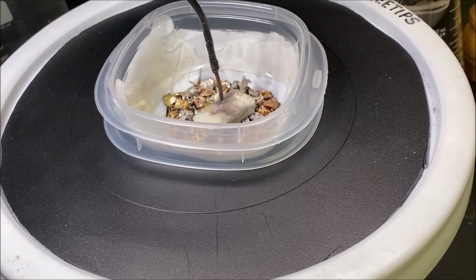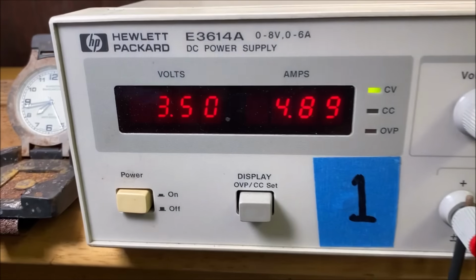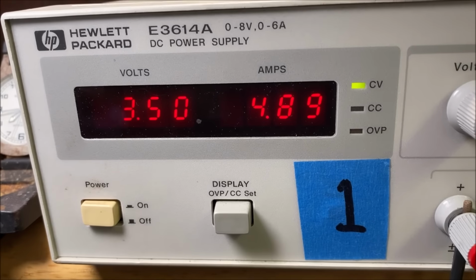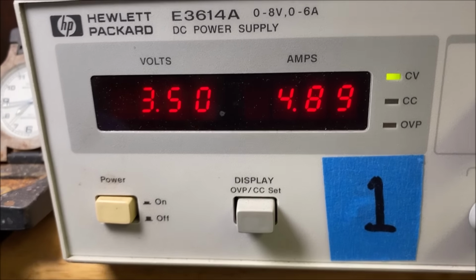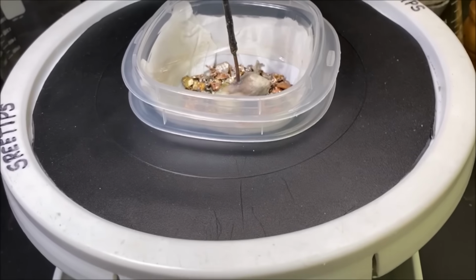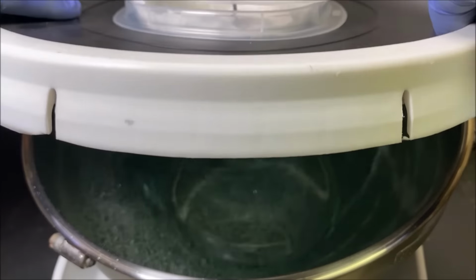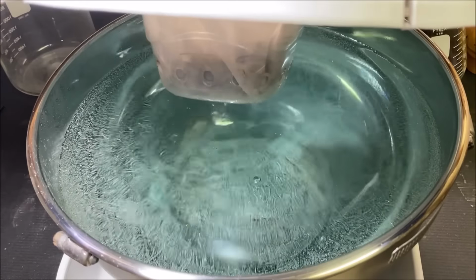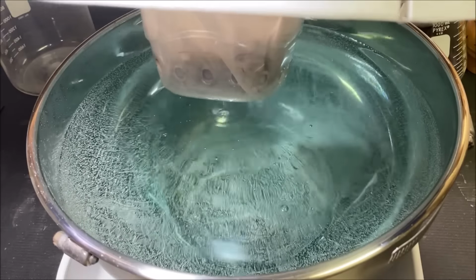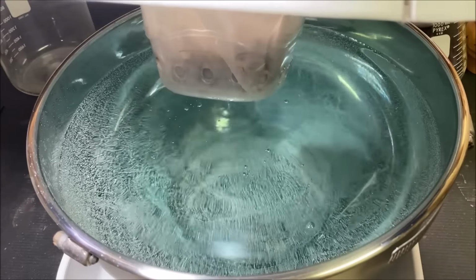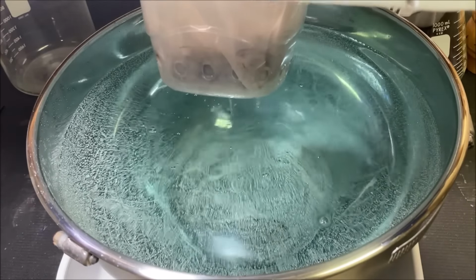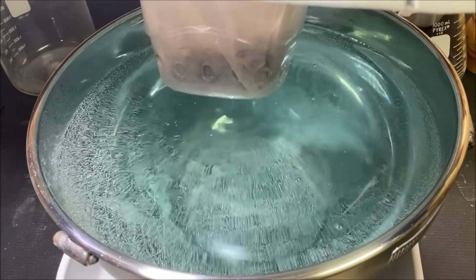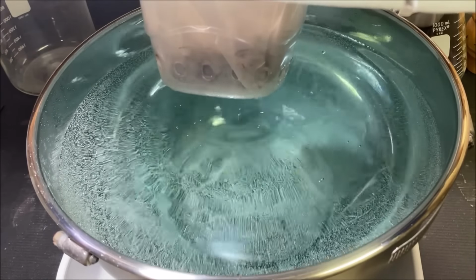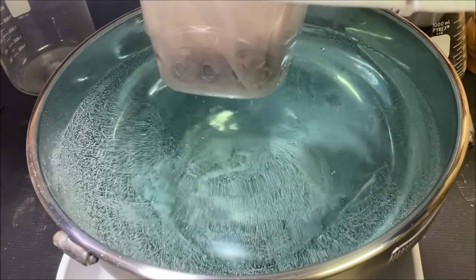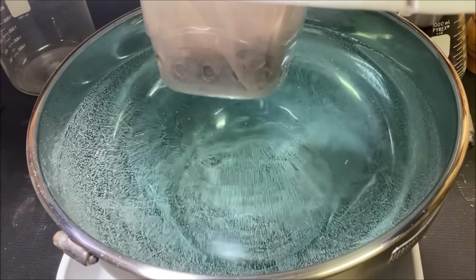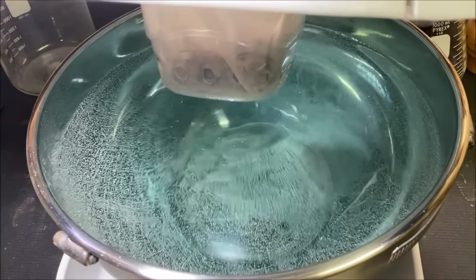The cell's been operating now for about, I guess, about an hour. There's our current flow. 3.5 volts in constant voltage mode. Let's take a look down in here and see what we got going on inside the cell after about an hour of operation. Oh yeah, you can see the silver crystals have already begun to form down in there. The solution has turned a little tint of blue, and that's from the copper that's in the impure silver up here in the anode filter basket. It's about 2% copper, 98% silver, and that's what we're running as feedstock. So this thing should crank out about 10 troy ounces of pure silver per day.